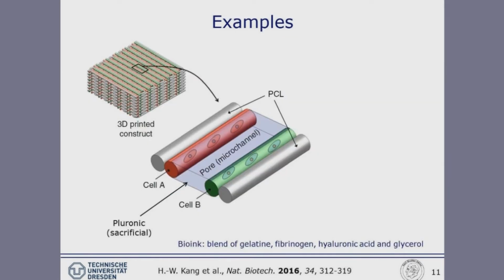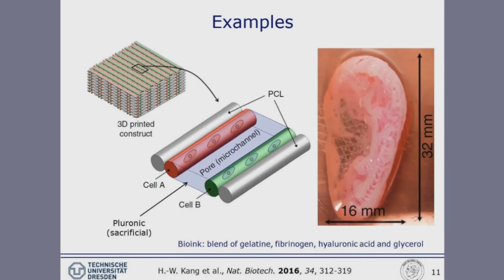Same direction, a newer paper coming from the Atala group, Wake Forest, United States. They made more or less the same, but additionally added a sacrificial material, Pluronic in this case, which can be dissolved after the printing and stabilization process so that an overall macroporous construct can be generated. And also they have been able to print such a human ear-like construct based on this combination, again using PCL as the mechanically stable polymeric material.